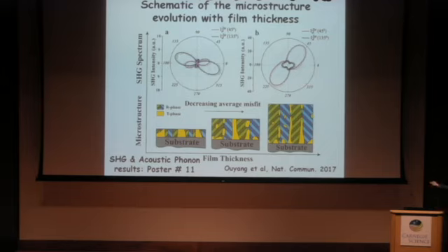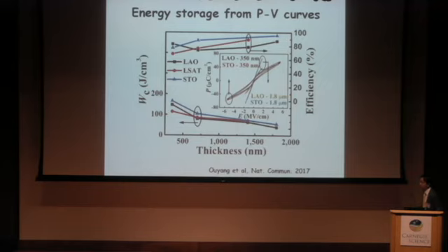So on the left is the SHG spectrum for the thinnest film, 350 nanometer. And this one is for the thickest one. You can see the intensity actually grows almost twice. So based on the TEM, XRD, and the second harmonic results, I can show you the schematic of the structure. When the film is thin, the dominant structure is T and R. When the film grows thicker, you have dominant rhombohedral structure, and you have some spots. When there's a highly stressed region, you can have tetragonal phase there to relax the growth stress. So that's the structure that we envision from the experimental results.